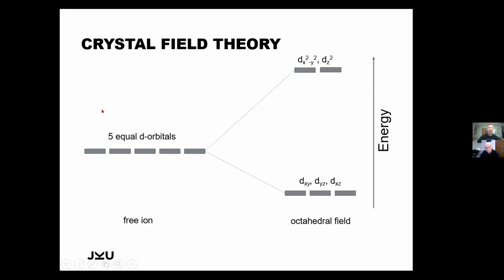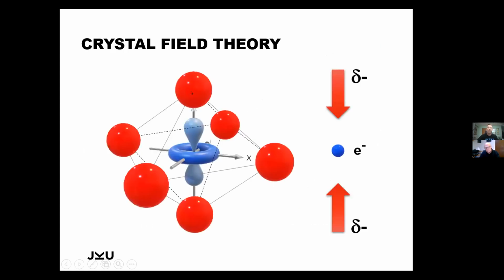So instead of having 5 equal d orbitals for the free ion, when the chromium is in a crystal field, which is a crystal lattice in all of the explanations that we use, then we have a splitting of different orbitals and therefore different energy levels. And this is different if we have an octahedral field or a tetrahedral field, and it depends also on the shape of the field. Here we have the oxygens along the z-axis pushed together a little bit. You see here these delta minuses pushing towards the electrons, and therefore you have a shift in the electron level or in the energy level.